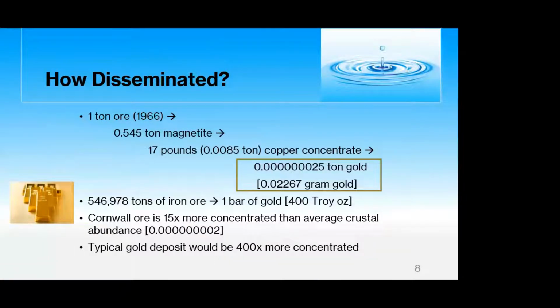So we now know that the gold at Cornwall was disseminated within the ore, but just how disseminated was it? I used ore production data from 1966 to give you an idea of how disseminated the gold was at Cornwall. On average, 1 ton of iron ore produced at Cornwall in 1966 yielded about 0.5 ton of the iron mineral magnetite. That same ton of ore yielded about 17 pounds, or 0.0085 tons, of copper concentrate. Further processing of the copper concentrate yielded the copper, gold, and silver, as well as additional iron.